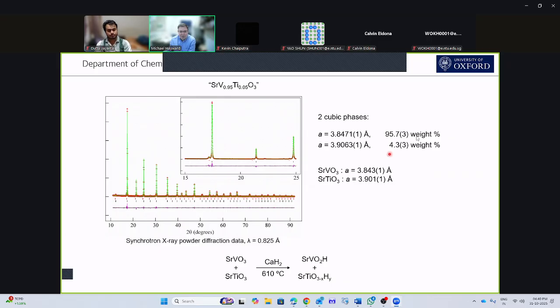And in fact, we've got 5% by mass SrTiO3, and we put in 5% titanium. And so what we can see is we haven't made a mixed phase compound at all. We've just made the two constituent single transition metal perovskites. And so when we reduce them, it's not surprising we get the two oxyhydrides. So how do we get around this?